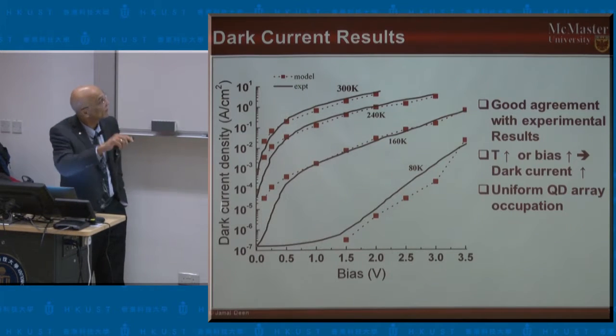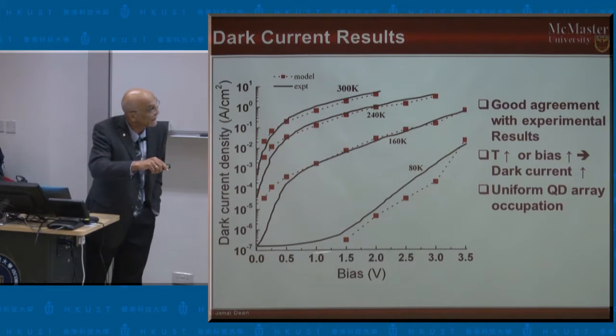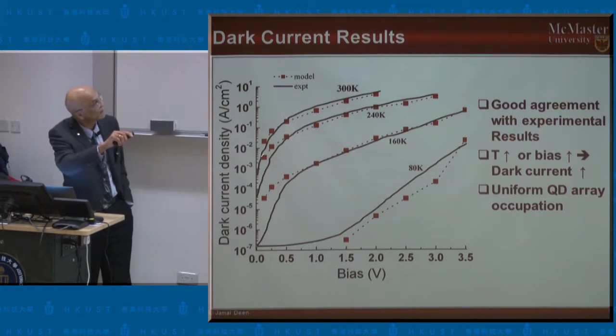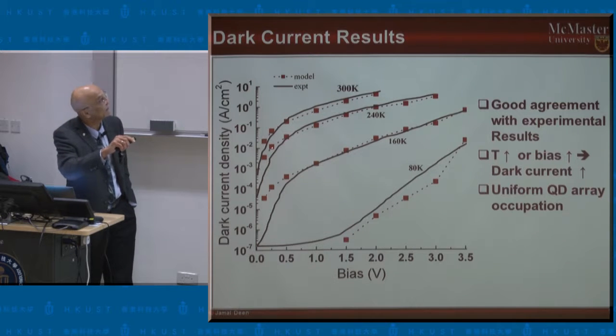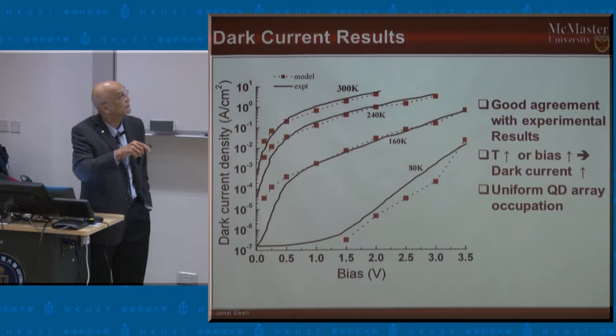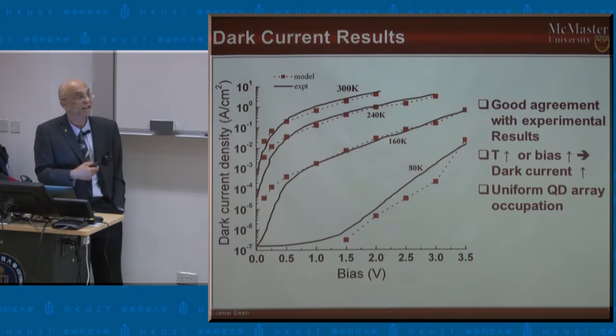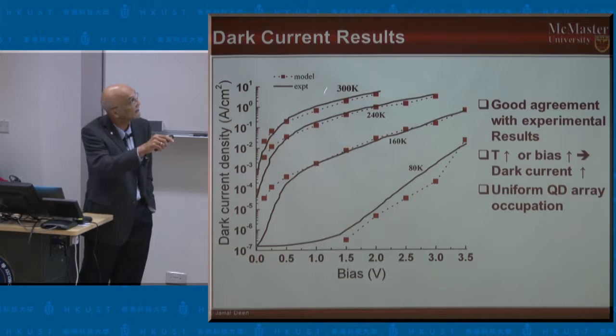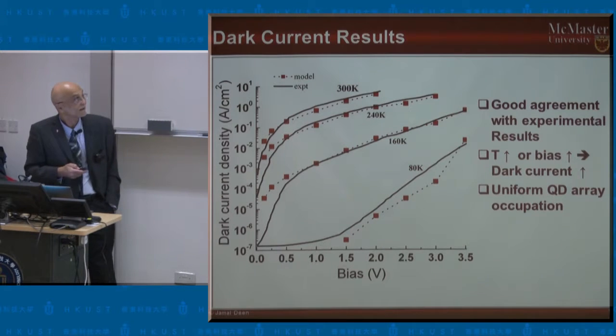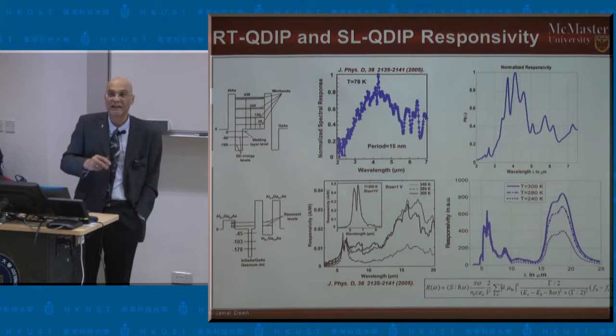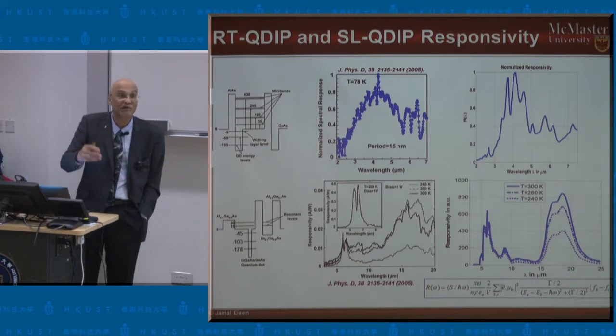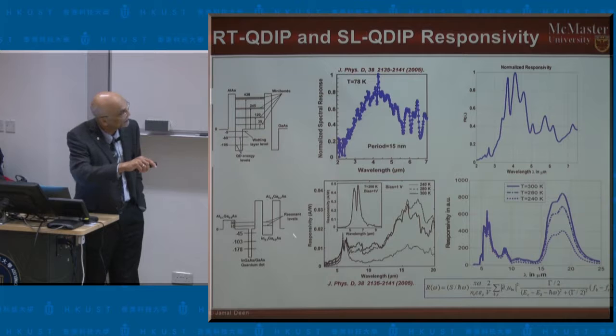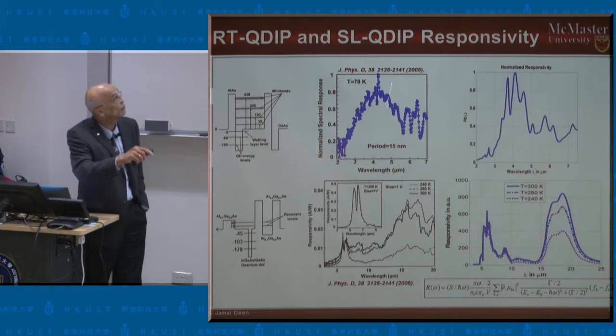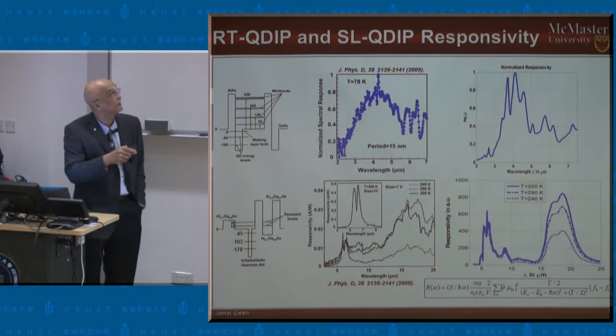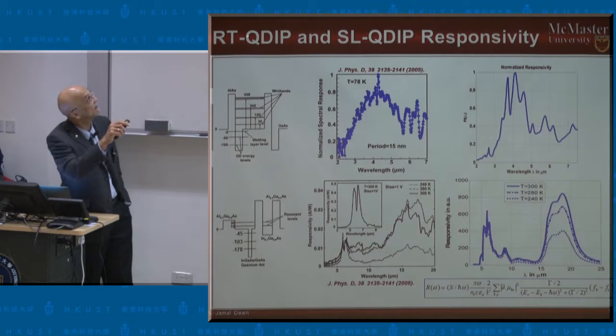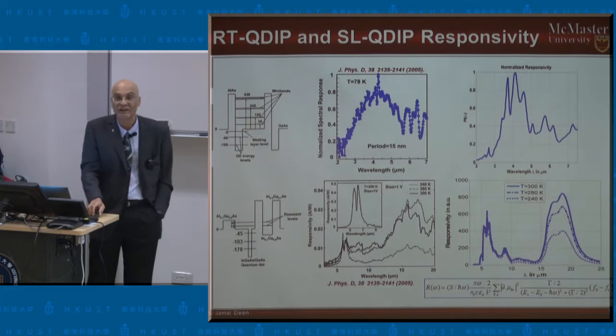This is an example of a computation of the dark current density as a function of biasing condition using the formulation. So again, you can see that the model is relatively well calibrated. The symbols are the model, the solid lines are the experiments, and you see we can predict the experimental results from 80 degrees Kelvin out to 300 degrees Kelvin. So once you have such a model, you can benchmark it again against other performance characteristics. So here again, we're looking at responsivity as a function of wavelength for 2 different devices. Now these are more sophisticated devices. So this one here is a resonant tunneling quantum dot infrared photodetector.